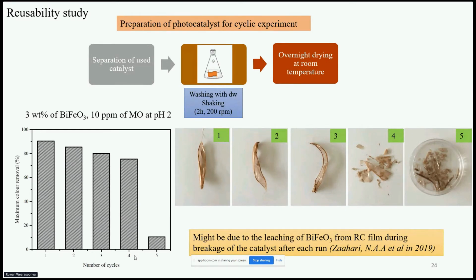Those conditions are 3% of bismuth ferrite, 10 ppm of methyl orange, and pH 2. So the reusability study was conducted using these best conditions. After the first experiment, the catalyst was washed with distilled water at 200 rpm for 2 hours and dried overnight before the second experiment. This catalyst washing and reusing in the degradation experiment was repeated until 5 cycles.